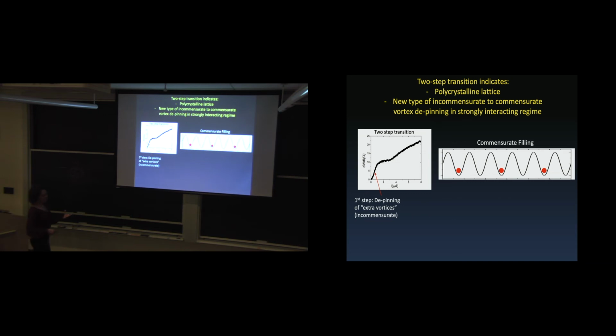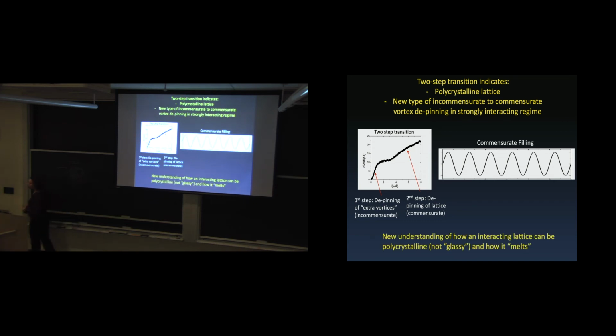And this is interesting. It tells us that it's not that all the vortices just depin at once, nor does the whole thing depin, but it's a polycrystalline lattice where individual vortices leave, then they leave behind a commensurate filling where nothing happens for some time, the resistance is constant, and then at the second step, all the vortices leave, and we end up in just a vortex flow state. And so for us, this was interesting because it gives us some new understanding of how this sort of interacting lattice can lead to a polycrystalline and not glassy state, and also how it melts.